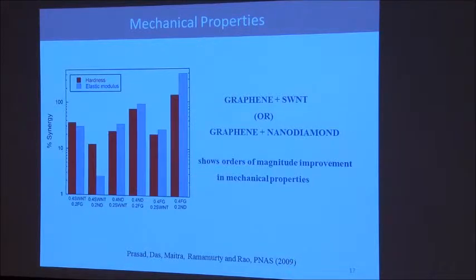What is more interesting is work we published in the Proceedings of the National Academy of Sciences about 3-4 years ago. When you take graphene and put a small amount of another nanocarbon like a nanotube or nanodiamond, 0.1, 0.2%, there is enormous synergy in mechanical properties, and this can be exploited even for practical purposes.